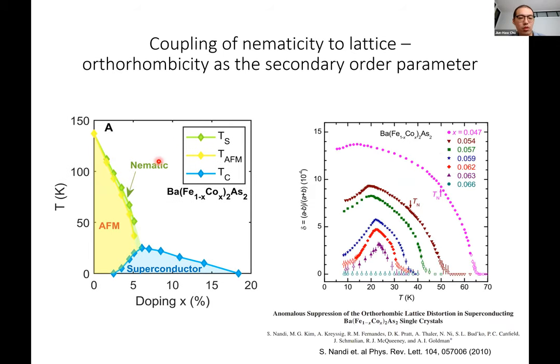And then indeed, when you do X-ray diffraction measurements, measuring the crystal lattice below the nematic phase transition, you can see the orthorhombicity, which is defined by the a lattice constant minus the b lattice constant divided by a plus b. That develops below the phase transition, following a mean field behavior. And what is really interesting in this pioneering work by the Iowa State group is that they found that this structural transition, the lattice distortion, is suppressed once the system enters the superconducting phase. So this really implies that the superconductivity is competing with the orthorhombicity, and that the structural distortion is really just a secondary order parameter that follows the primary electronic order parameter, which is really the driving force of the phase transition.